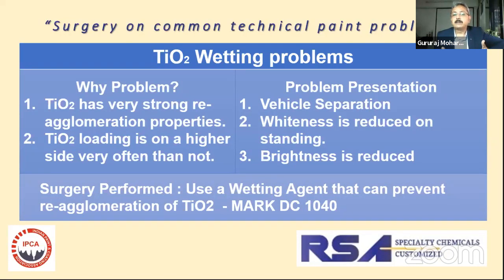So what happens when the titanium has reagglomerated? You get a clear varnish, a violet tinted varnish at the top, which is called vehicle separation. The whiteness and the brightness of the titanium is reduced because the effective titanium has come down. So all these problems happen because of your reagglomeration.